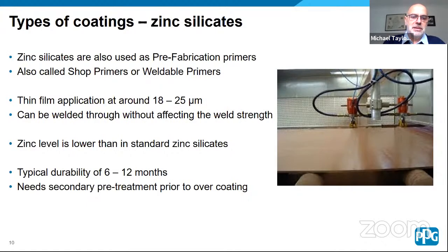The zinc level in this is usually lower than in standard zinc silicates, up to about 40% zinc by weight in the dry film. The reason for that is that if you put too much zinc in, it can affect the weld, but also because of the zinc fumes that are given off during the welding process. All the prefabrication primers, shop primers, etc., would be tested for health certificates as well before they're used in this way. If you just have a prefabrication primer on at about 18 to 25 microns, typical durability, depending on the environment for that type of coating, will be around 6 to 12 months. But you would need to do some secondary pre-treatment prior to overcoating it.